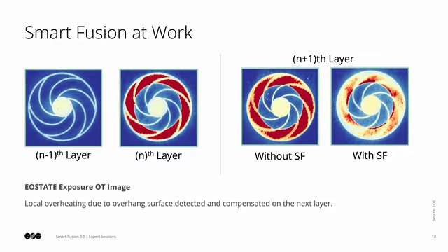Smart fusion technology uses OT pictures to detect such areas and regulate the process in a very precise manner, namely with 100 micron resolution, and decreases the energy on these areas to avoid residual stresses and overheating.